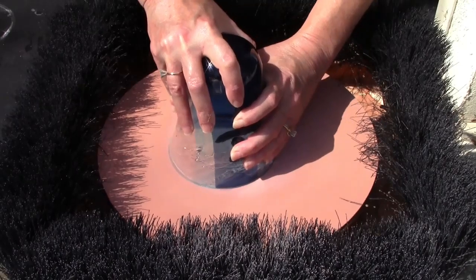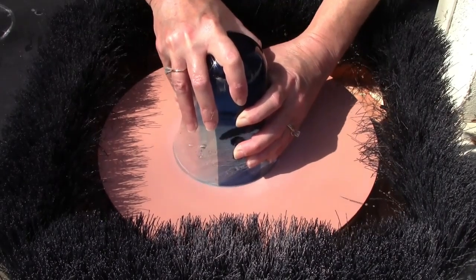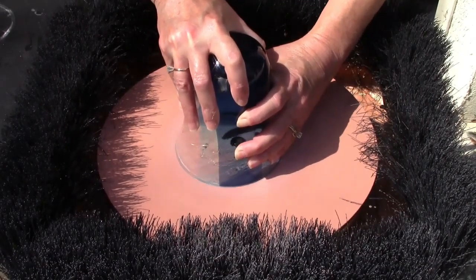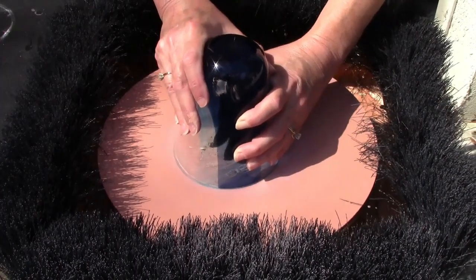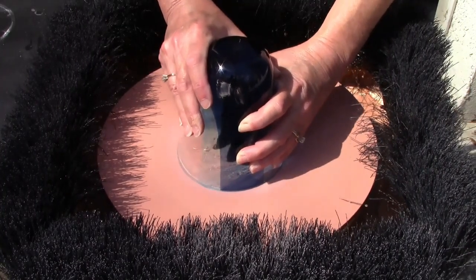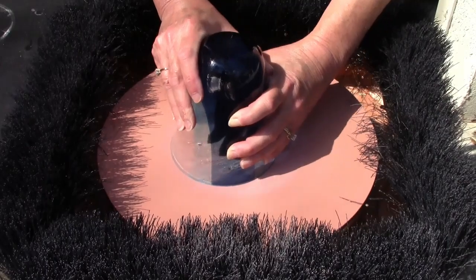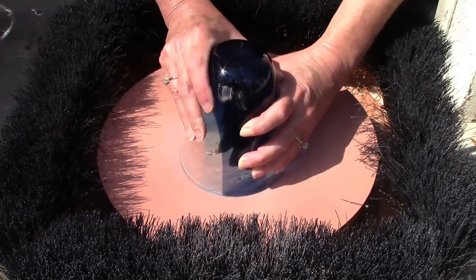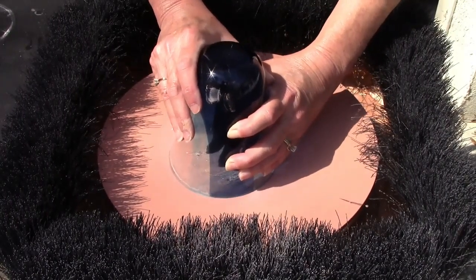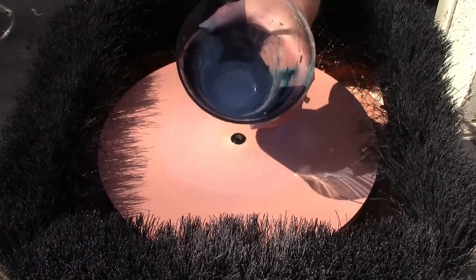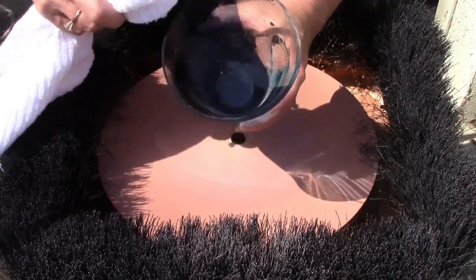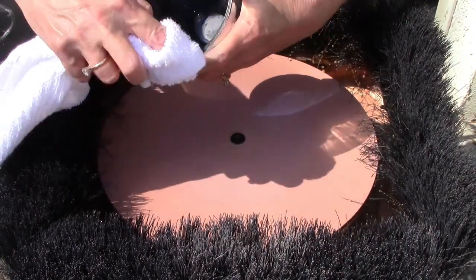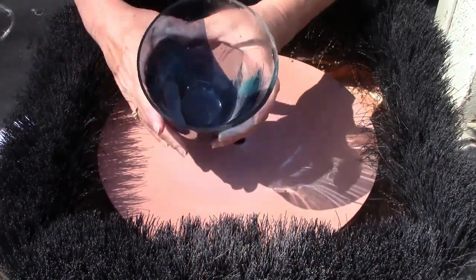I am applying a little bit of pressure here to create some friction, which helps improve and brings that shine out of the edge of the glass. Now this is where the previous step is really important. If the previous step hadn't been done where the edge was uniform, you'll never get a uniform shine on that edge either. So patience, and then dry the edge, check it out. Let's see what it looks like. Let's see if it's uniform and shiny all the way around. When it is, then we consider the piece done.